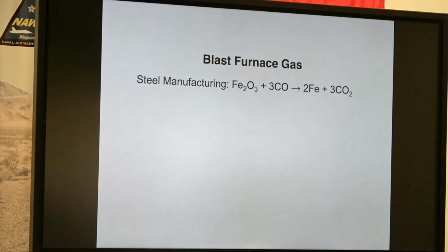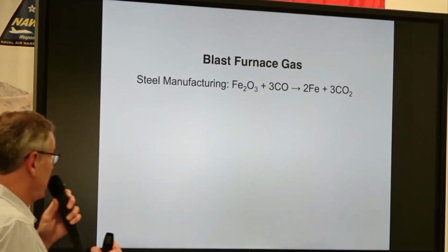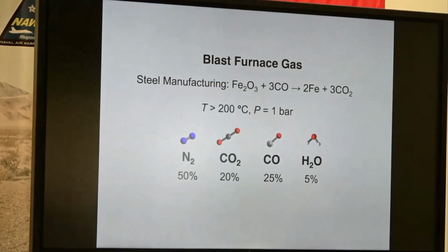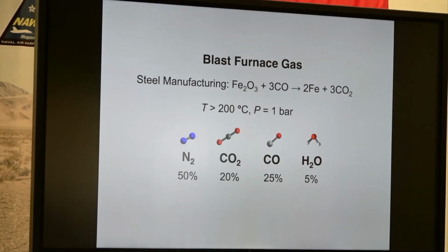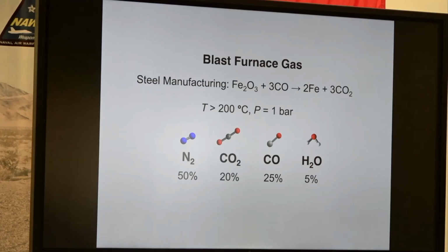And so we can take a blast furnace gas from steel production as an example. So in producing steel, you're reducing iron oxide with carbon monoxide and creating CO2 and iron. That CO2 then winds up in an exhaust gas that has this composition, and it can be much higher in temperature, but above 200 degrees C. It starts out much higher, of course. So here we've got nitrogen, CO2, CO, and water. You'd like to grab CO2 so it doesn't go and warm our planet. You'd like to grab carbon monoxide so that you could reuse it in making more steel. You really don't want to just burn these or exhaust them.